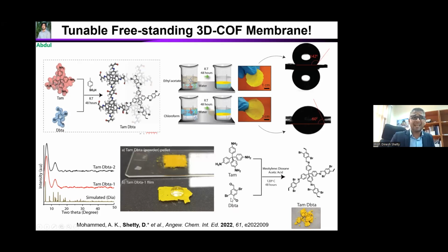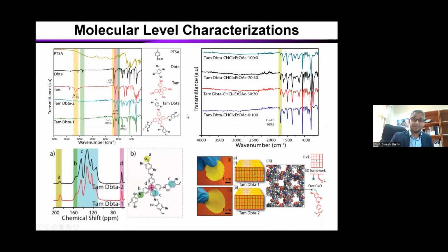On the other hand, if you do the same synthesis in traditional solvothermal synthesis, then we again end up getting a 3D COF, but this COF has a hydrophilic nature, not hydrophobic nature. So this is the crystallinity of that COF. It is a 3D COF with polymorphs, and then we did simulation to understand the structure and everything. But that is not important here. The important thing here is why this phenomenon is happening, right? So to understand that, obviously, first we did a basic molecular level characterization.